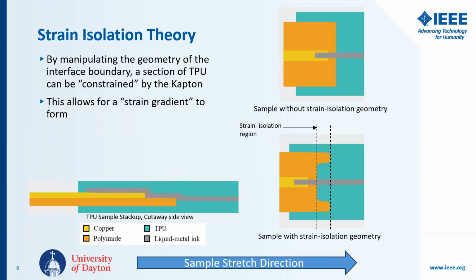So in order to reduce that, we can further spread out the length of the modulus of elasticity change at the boundary layer between Kapton and TPU by manipulating the geometry of that boundary. Adding a concave section of the boundary will constrain a section of the TPU that is trapped in that section and allow a strain gradient to form. This keeps the conductive material from cracking when it's stretched. So we can see right at the interface of the Kapton and TPU, we've carved out a section of Kapton, and that allows us to set up a strain gradient.